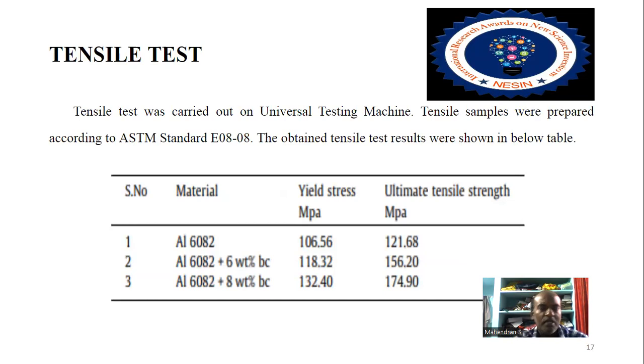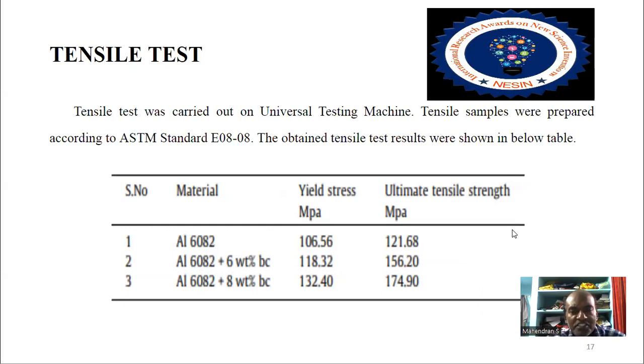Next one is tensile test. The tensile test was carried out on a universal tensile testing machine. The test samples were prepared according to ASTM standard E8. The obtained tensile test results are shown in the below table. Aluminum 6082: the yield stress is 106.56, ultimate tensile stress is 121.68. Next, aluminum 6082 plus 6 weight percentage of boron carbide: 118.32, 156.20. Next, aluminum 6082 plus 8 weight percentage of boron carbide: 132.40, 174.90. These are the ultimate tensile strengths that are noted.